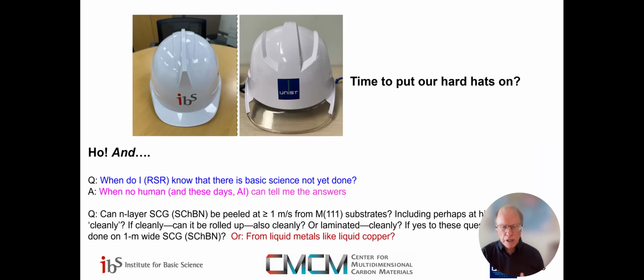So in our center, we're the Institute for Basic Science, we need to also do basic science. So I can tell you, I don't find anything on peeling, particularly peeling at high temperatures. There are a few nice studies of peeling of polycrystalline graphene, for example, from copper surface at room temperature, but high rate peeling and being close to the growth temperature, maybe dropping a little bit so that the surface is still stable. But liquid copper, we'd have to make sure that it remains liquid, melts at 1085 degrees C.